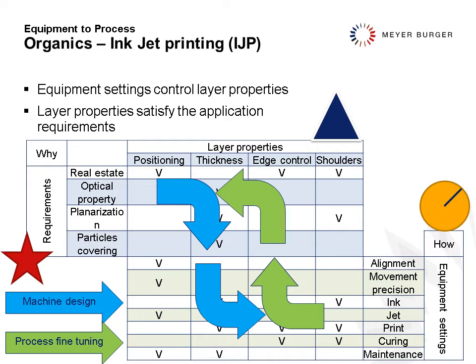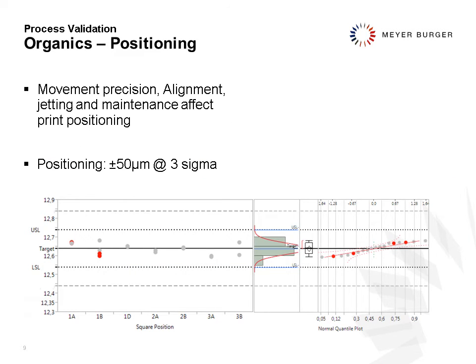So let's have a look at positioning. What can be achieved, for example, in our machine? For printing, by coupling the movement precision, the alignment, the jetting, and the maintenance, all of this affects the print positioning, and therefore we can achieve positioning of plus minus 50 micrometer at 3 sigma. Here's an example of placing a certain edge at a certain distance on a square position, and we demonstrate this on several plates in several locations, making this measurement, and then we demonstrate this plus minus 50 micron.